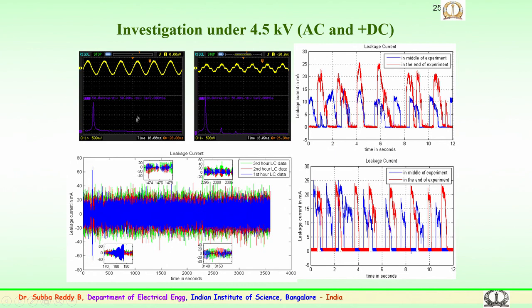During the process, the leakage current for various samples was measured. One of the experiments is conducted at 4.5 kilovolts, both for AC and DC application. You can see the discharges during the process, and these discharges, which are continuous in nature, have been recorded using a National Instruments module where long duration data could be captured and used for analyzing the data. So, we have seen various types of leakage current data here for 1, 2 or 3 hours, which shows the increase in magnitude for a different time span, and this shows the leakage current in milliamps and time in seconds during the middle of the experiment. So, this is how the performance is monitored.